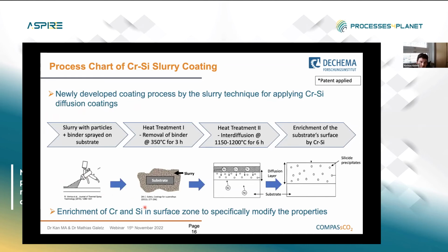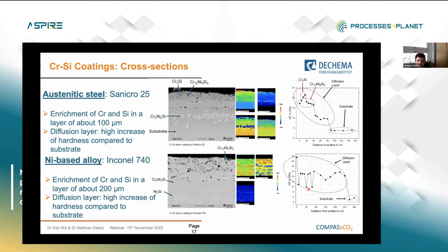So it needs a binder removal at around 350, and then the second heat treatment is still pretty high, in the range of 1150 to 1200 degrees C for around 6 hours. But then, for example, on nickel-based alloys, it's still in a range where we can heat treat, and then we have nice coatings, as you will see on the next slide. Here we have two micrographs, one on a Sanicro 25. This steel can also be heat treated at those temperatures.